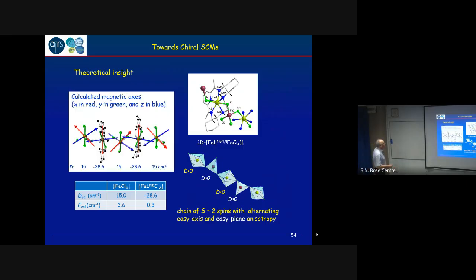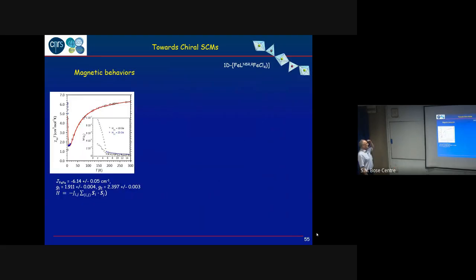So this is just a picture of the anisotropy in these centers. Again, we have the actual anisotropy of the seven-coordinated system, which is perpendicular to the pentagonal plane. And this is the magnetic behavior. What we see here is roughly the behavior you would expect for a system with antiferromagnetic interaction. This is shown by the decrease of χT. It comes down to a given value and then it goes down. This is typical for a ferrimagnetic chain. So you can analyze this behavior to extract the exchange.